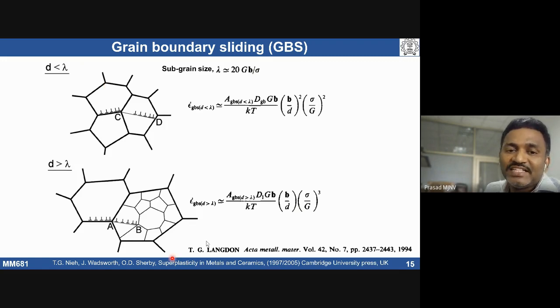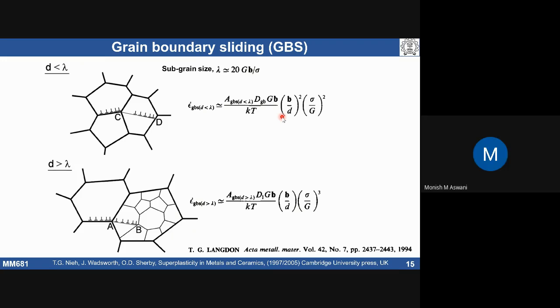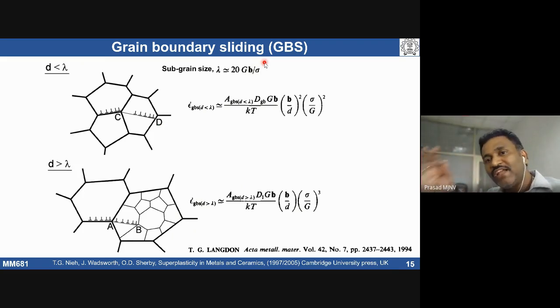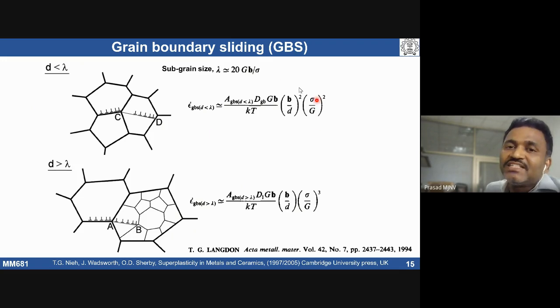So this is the mechanism which happens, grain boundary sliding, in coarse grain materials. Here is the constitutive equation for grain boundary sliding which happens in fine grain size materials, like superplastic materials. Is it clear? Yes, sir. So what I want to say is that grain boundary sliding can take place in both coarse and fine grain materials. Superplasticity can be observed only in fine grain materials. When I say fine grain, the grain size should be equivalent to or less than the subgrain size. In that case, we have to use this equation. In coarse grain materials, we also see grain boundary sliding, but there we have to use this kind of constitutive equation. Any doubts?